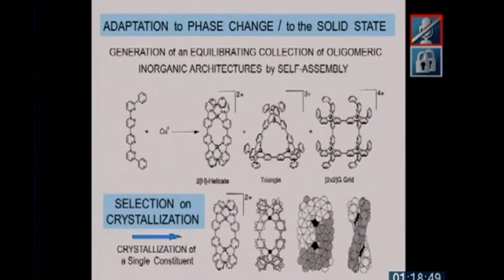When you have a mixture and you crystallize the components in that mixture, you want simply to purify. When you have a mixture, you hope that one component will crystallize and the others remain in solution. That's the normal crystallization. However, when what is in solution is dynamically interconverting, then the situation is very different. Take this ligand here, treat it with copper-1, and you find by nuclear magnetic resonance that you have in solution a mixture of equilibrating, and insist, a mixture of equilibrating species, a helicate, double helix, a triangle, and a grid. Okay? Now, if you crystallize this, if you put it in conditions of crystallization, the solid contains only the helicate.